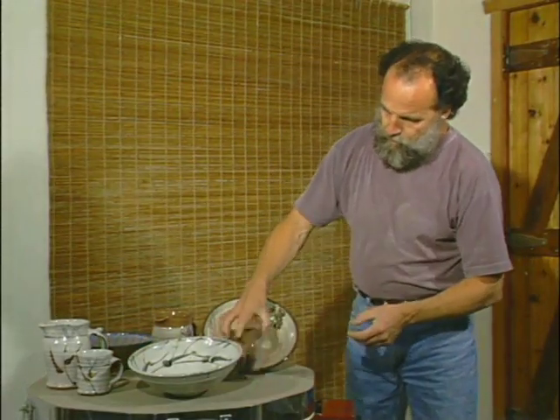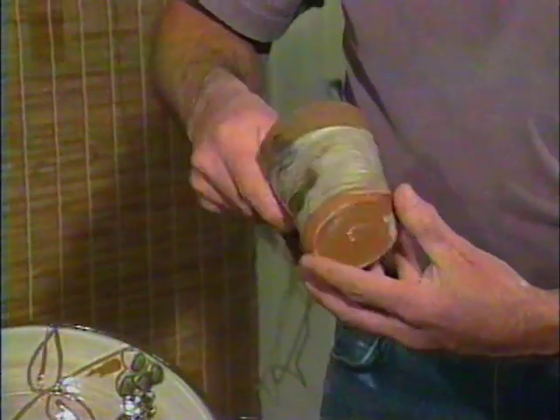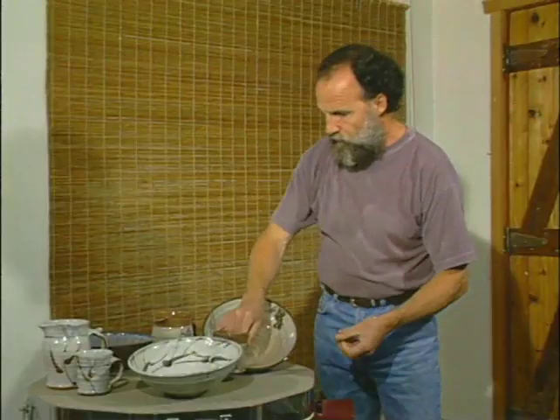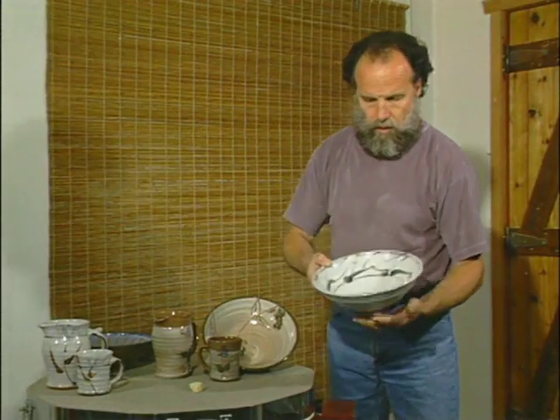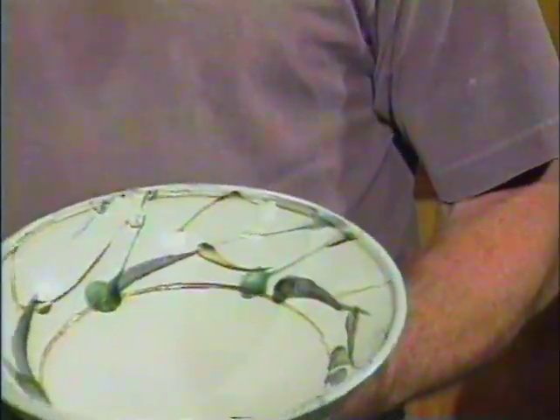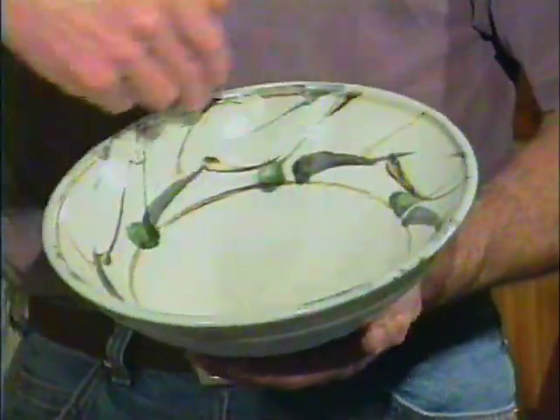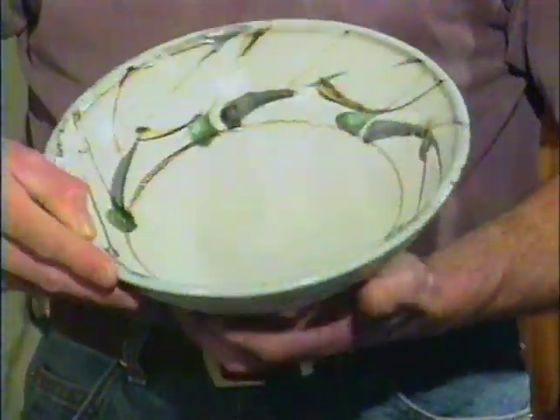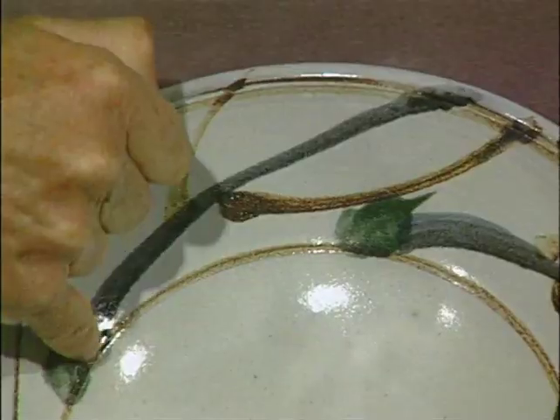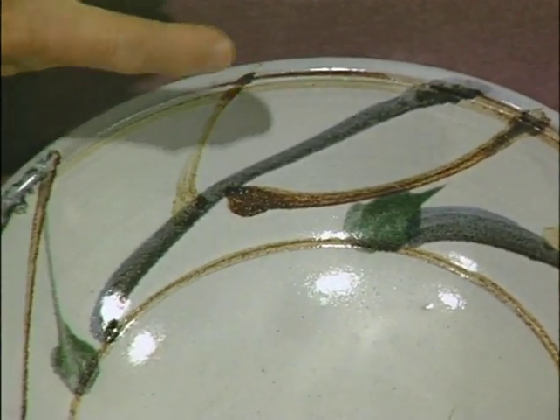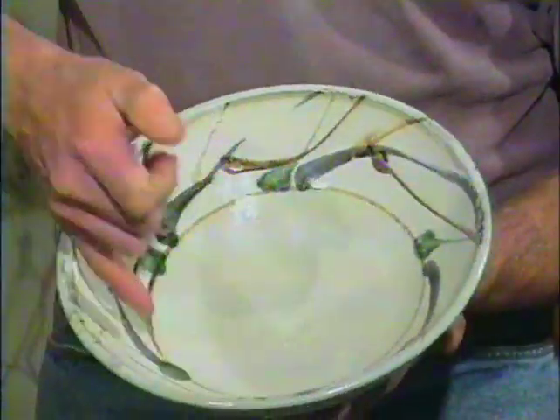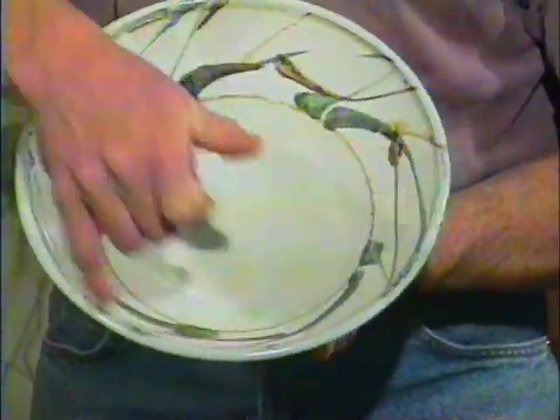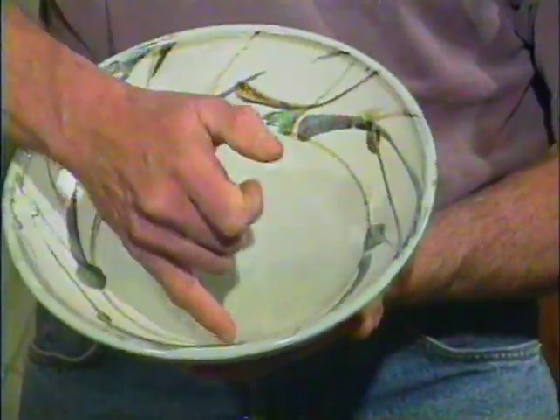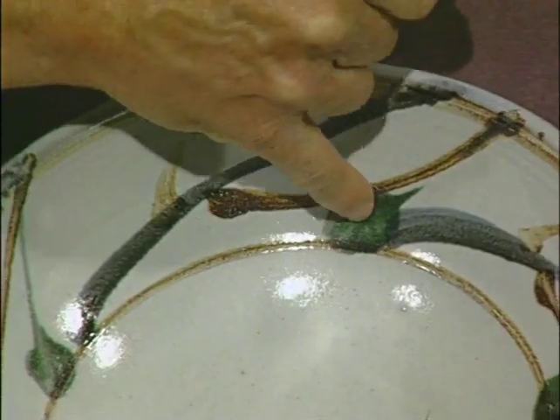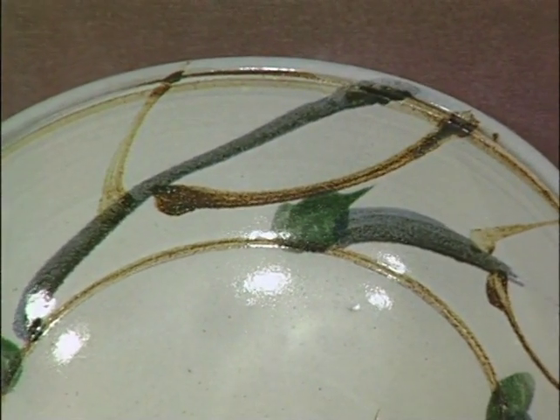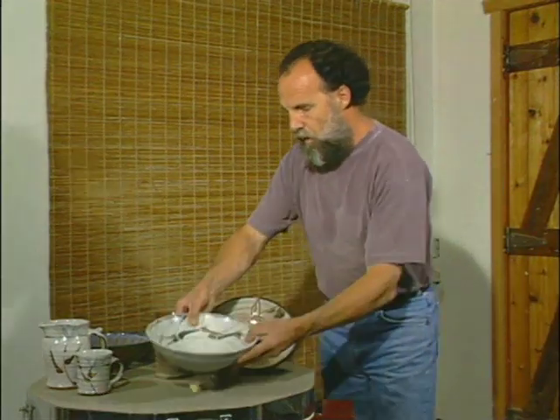And these pots here have been treated in a similar way, exactly the same technique really. On these ones, I've initially covered the whole thing with the opaque white glaze, and then I've decorated on top with oxides mixed with water with a brush. Here we've got rings of iron, and here the copper carbonate blue, iron again, and then lastly a splash of the green glaze applied with a brush. And this is the base glaze with a little chrome added to it.